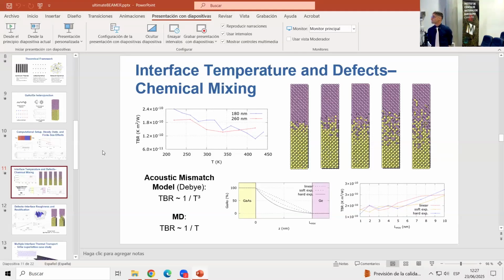There are a couple of works by Natalio Mingo and Jesus Carrete, like 7-8 years old, where they basically do this sort of thermal tuning in nitrides, I think, by doing a graded composition change. In a very simple picture, this helps heat to be transferred from one side to the other one. So I was just thinking, this is disorder, I understand it's different, but do you see why this happens? Why when you increase the thickness, things get actually worse?